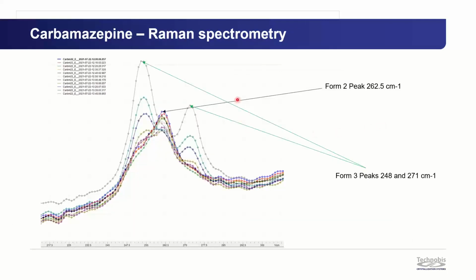We can also see this change by the Raman. So we initially start with the form 2 peak, and then this gradually decreases over time, and we see an emergence of the form 3 peaks here and here. So we'll be able to track when something is fully converted and when we've removed all of the form 2, so we're confident in the crystallization process.